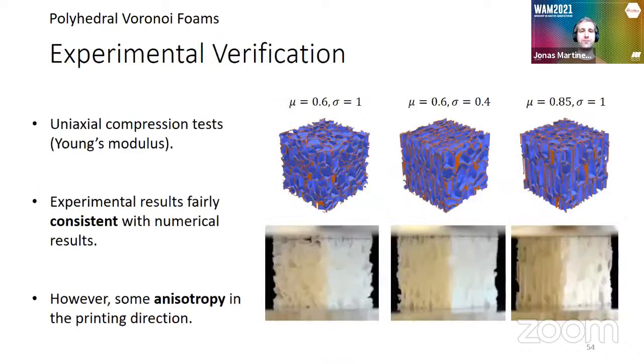And finally, we also did some very simple uniaxial tests to see if there is a good agreement between the Young moduli. And of course, printing is always introducing anisotropy in the direction. So we also observed some anisotropy in the printing direction with respect to our numerical method.